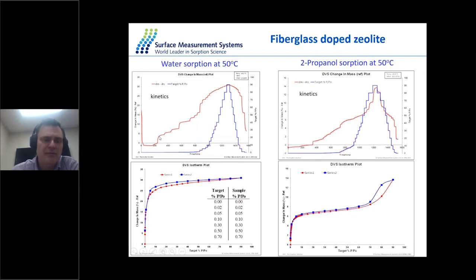You get almost 5-8% uptake. So again, you get to look at the type 1 isotherms at 50 degrees for water absorption on the fiber doped zeolite. So what you can see, by varying the different probe molecules, we can get different types of isotherms. So in this case, for water vapor adsorption, isotherm at 50. For fiber doped glass, I can get nice type 1 isotherms, and I'm able to go to extremely low partial pressures, which we won't be able to obtain, let's say, in the flow systems.